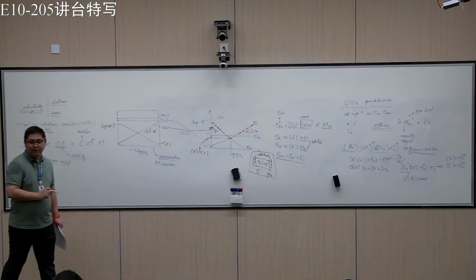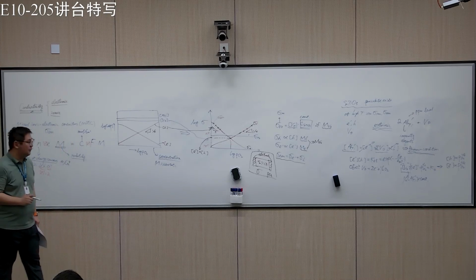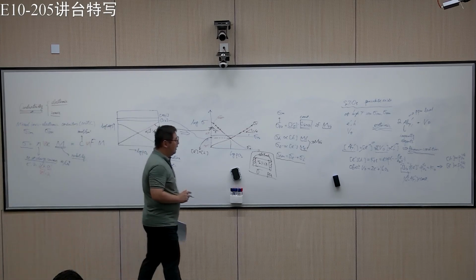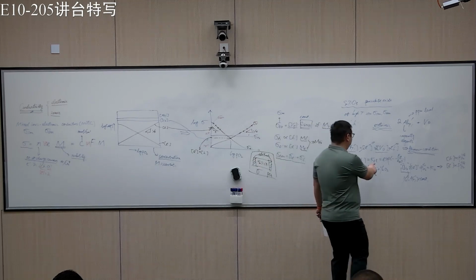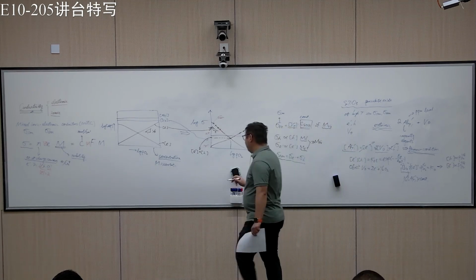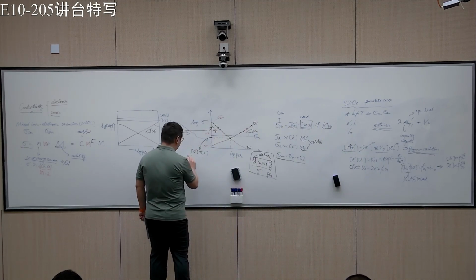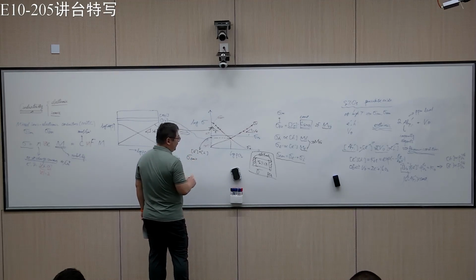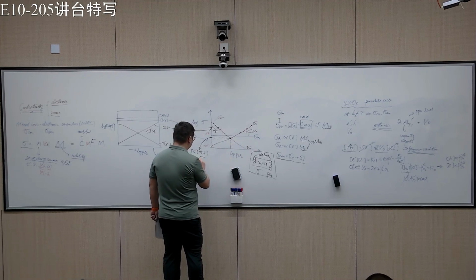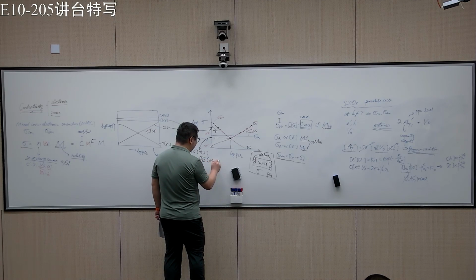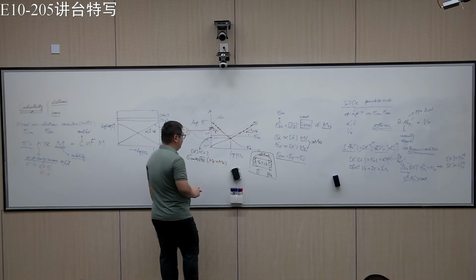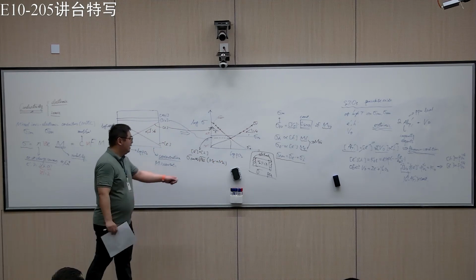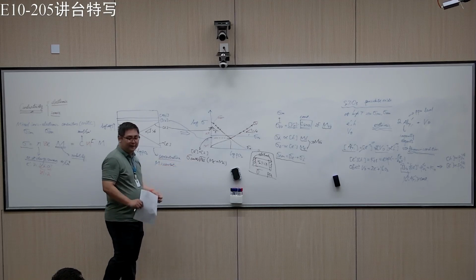Electron and the hole concentration, they are the same, right? So they are basically square root of this one. And then here, the electronic conductivity should be proportional to square root of K_el times electron mobility plus hole mobility. Okay. In a minute, we'll know why that's important.